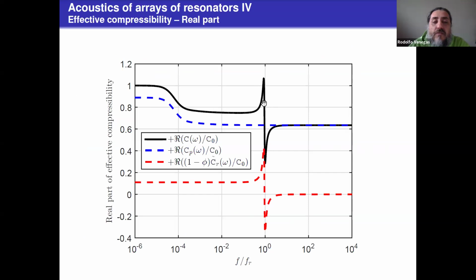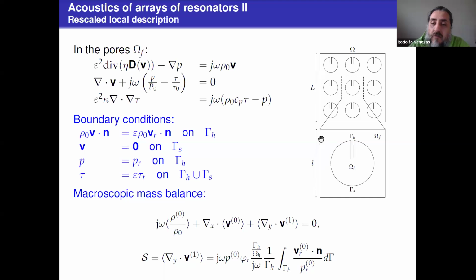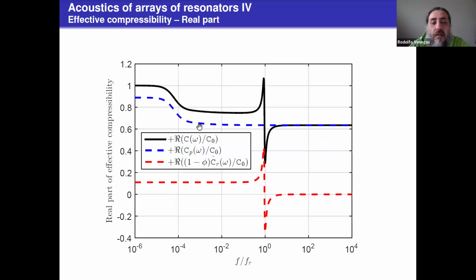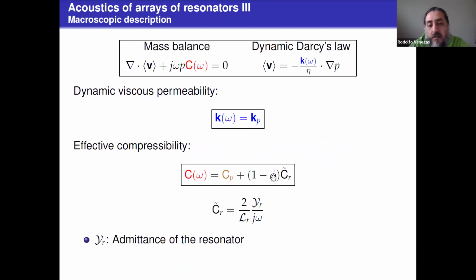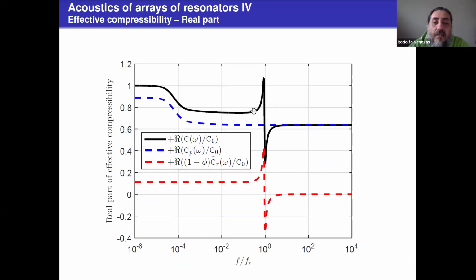So in black, we have the compressibility, the real part of the normalized compressibility of this array of resonators, Helmholtz resonators. And in blue is the compressibility of, let's say, what's happening around this resonator, the pores, which follows a classical trend. And in red, we have the compressibility coming from the resonator itself. So the black curve is a combination of the blue and the red one, as shown by this expression here. That's in terms of the real part.